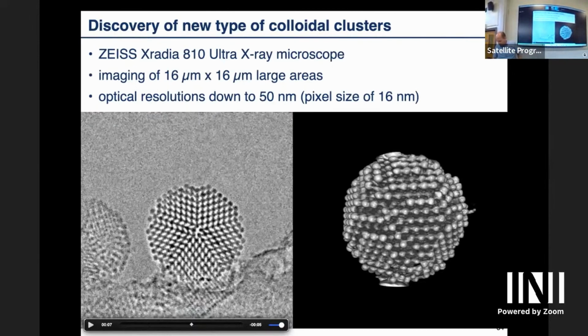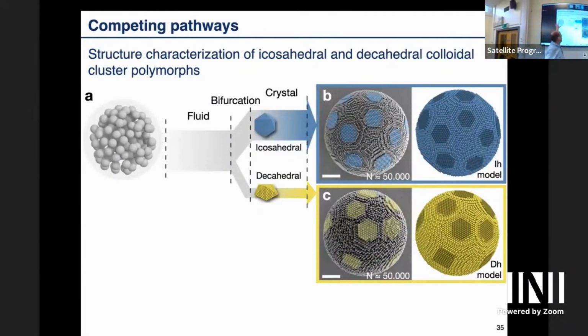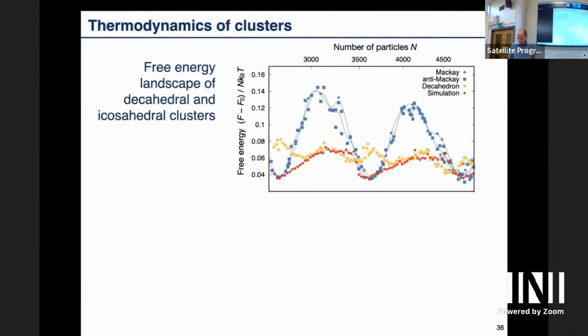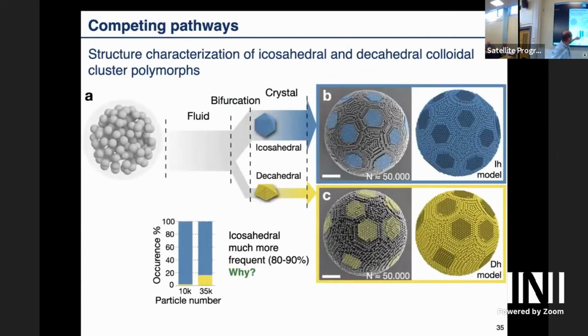I don't have much time, I'm running out of time, so I will skip a few slides, but I will just point you to the most important parts. Namely, there is now a bifurcation. You can get icosahedral clusters, you can get decahedral clusters, and it depends a bit on the size. So what I told you before was a bit of a simplification, namely that there's another line here in the free energy. This is the same diagram we've seen before. And now with yellow, we have the decahedral cluster, and the decahedral cluster sometimes can compete with the icosahedral cluster. But still, when we do statistics, depending on the size, for a small cluster, we see 80 to 90% icosahedral clusters, very few decahedral clusters, which is why I have not shown them to you before. They're super rare.